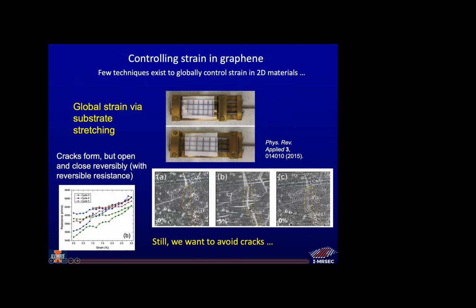So this crack here is maybe 500 nanometers. They're bigger than you'd expect to hop across. Okay, I see. Yeah. And besides that, because the cracks were sort of self-limiting, they tended not to extend across the whole device. We'd get just regions of cracks. And so the conductance was always going to be much larger going around them than even tunneling through small regions of these. That makes sense. Yeah. So I think that's what was dominating it.